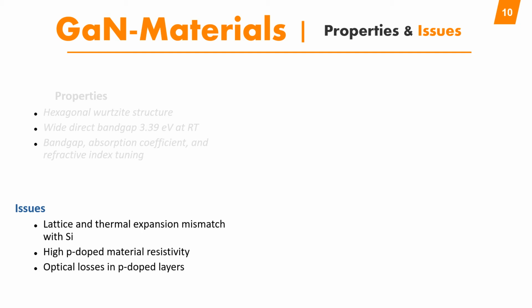So these properties, as I said in the beginning, are superior for optical applications such as laser devices, but there are also some issues during the integration with silicon photonic devices, especially with silicon, because there is a lattice mismatch and thermal mismatch of gallium nitride with silicon. There is high resistivity of the p-doped materials and also optical losses in the p-doped layer. Quickly, the high p-doped material resistivity is due to the low concentration and low mobility of holes inside these materials, and these materials are lossy because of their high absorption coefficient, which over time affects the light extraction efficiency and hence the quantum efficiency or quantum yield of the device.